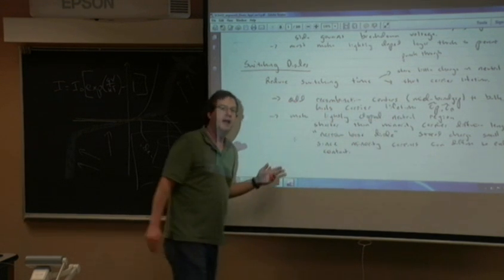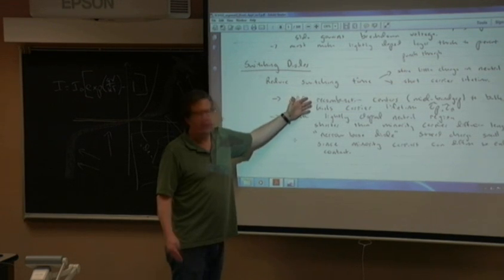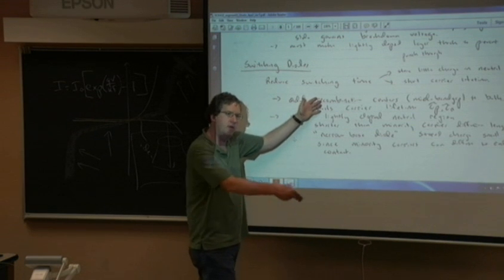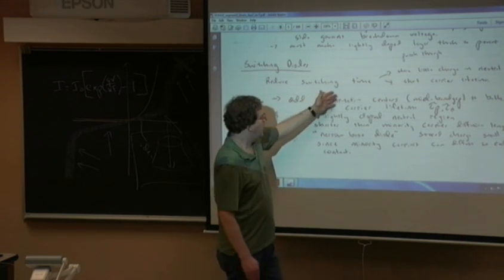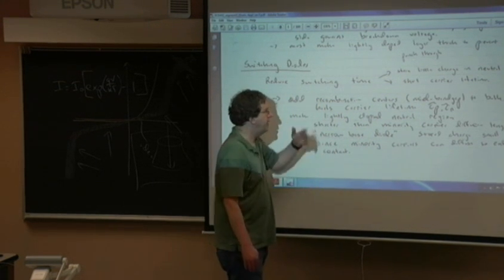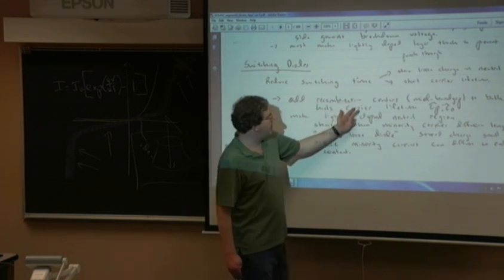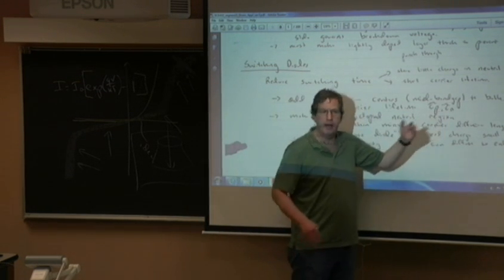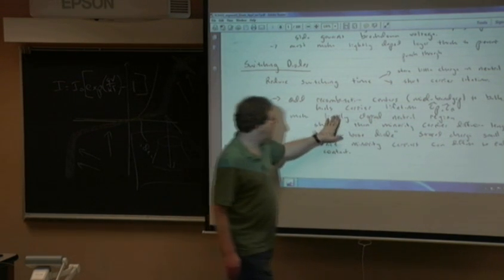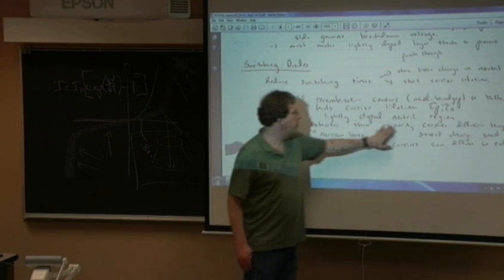The other is the carrier lifetime. We were talking about that in the live lecture this morning: adding traps, or recombination centers. Sometimes I use the analogy of stepping stones to cross a stream. Near mid-band gap is where they're the most dangerous. Add that to the material, and this kills, that's a K by the way, the carrier lifetime, the tau P's, the tau N's, everything. All the carrier lifetimes die. Also make it lightly doped, with a neutral region shorter than the minority carrier diffusion length.